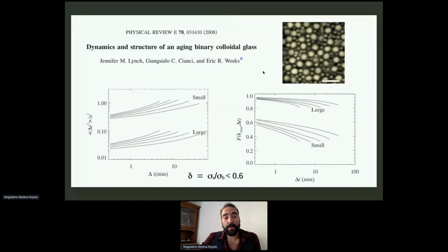And there is a lot of information, experimentally speaking, that confirms that approaching the glass transition in binary mixtures, which actually do not have such a large asymmetry, so there is not even the existence of a single glass or a double glass, but even in those conditions, there are enough experimental data that confirms that the dynamical quantities of both species evolve with the time of observation. And one would like to describe then this kind of transitions from a full non-equilibrium perspective, which already poses a new challenge for experimentalists, for people making simulations, and of course for the theoretical description of these systems.